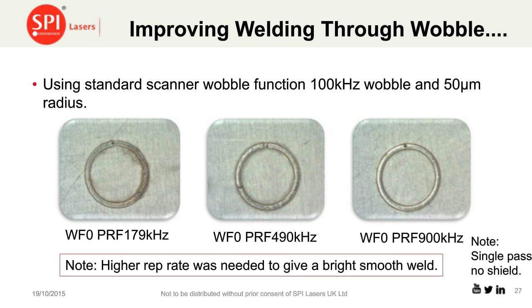One of the other things, well, that's basically just linear processing. One of the other things that is being more commonly adopted within welding, it's not a new idea, because back in The Welding Institute, back in the 80s, I believe, or even late 70s, we were looking at wobbling laser beams to improve fit-up acceptability on welding. So it's not a new technique, but it's a standard feature on scanners. But with the ability to wobble the beam through very small radiuses or diameters, you can actually extend or broaden the weld and still create very good results. And here, using this technique, we can generate bright welds through thicknesses of material up to about 0.5 millimeter, which are bright and smooth, and again, single pass, no shield.